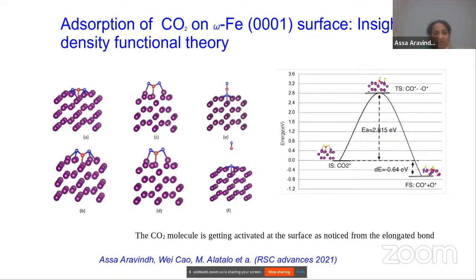And it is seen, as you can see here, that depending on where it attaches, the molecule is getting activated, and there is also a possibility of spontaneous splitting into O and CO. So this is a very interesting study, and in these calculations we can also see whether there is an activation energy barrier, and we can calculate all these things using DFT studies.